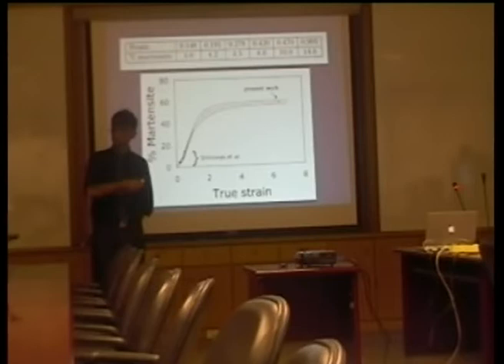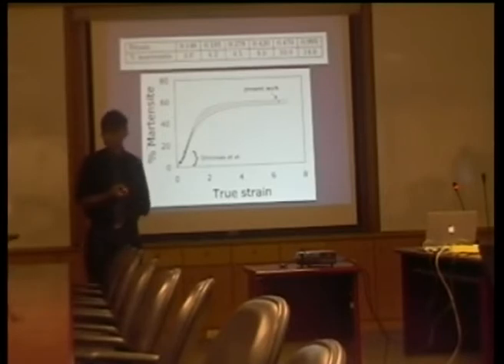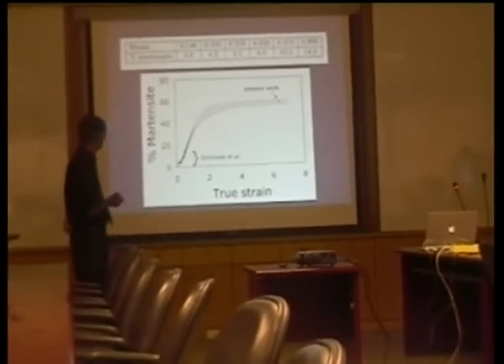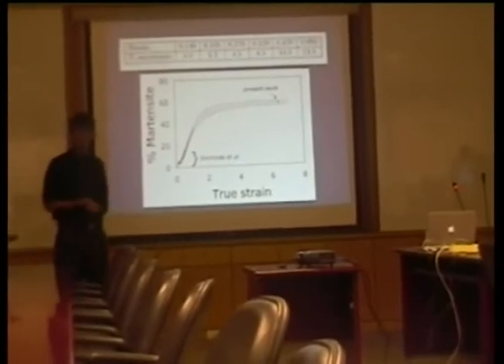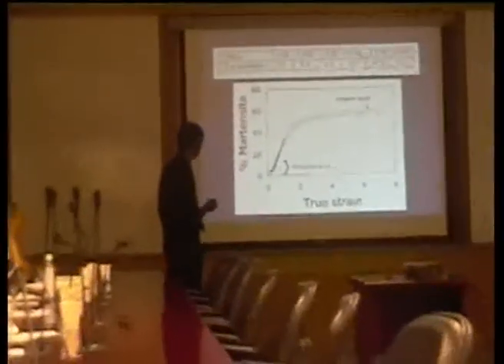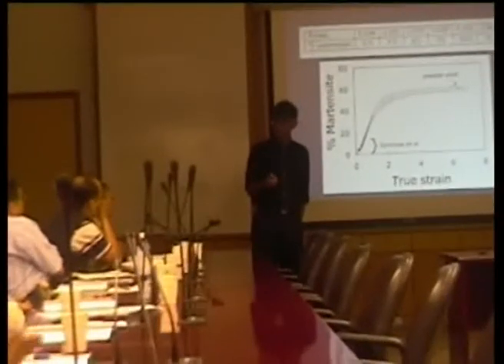Later on I will show you the theory we have developed independently to show that we should get mechanical stabilization at a strain of about 2. But of course we don't have any experimental data here. And this is where MIRDC could help us to deform this stainless steel wire to intermediate strains between 6 and this. We've already made the predictions and published them.